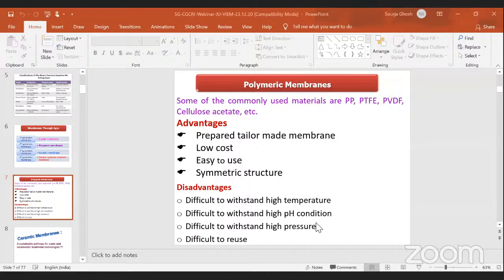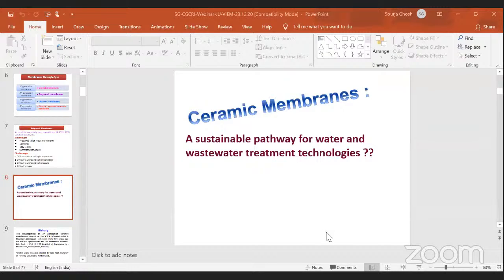If we go for polymeric membranes, the commonly used polymer materials are PP, polytetrafluoroethylene, polyvinylidene difluoride, cellulose acetate, etc. The advantages of these membranes are that they are easy to prepare, can be given tailor-made pore sizes, are low cost and provide a symmetric structure. However, such membranes carry some disadvantages also. That is the low stability in chemical and mechanical environments. These membranes are also prone to attack under harsh chemical conditions, and they cannot withstand high temperature. It is difficult to reuse such membranes, so they have a shorter life compared to their inorganic counterparts. So the ceramic membranes come into the picture here, and they provide a pathway of a sustainable nature for water and wastewater treatment technologies.